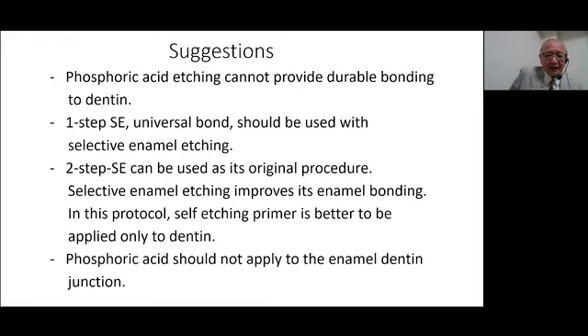Now, as a summary, I can suggest these for the bonding. So I can tell you that the phosphoric acid etching cannot provide durable bonding to dentin. Of course, the enamel bonding is good, but for dentin, we should not apply the phosphoric acid etching. We should apply the two-step self-etching adhesives. In the case of one-step self-etching adhesive, like the universal bond, we should apply the phosphoric acid etching to enamel because the bonding of the universal bond to enamel was not sufficient. This is because of many kinds of reasons, such as the difficulty of the removal of water and solvent and the difficulty of the polymerization.